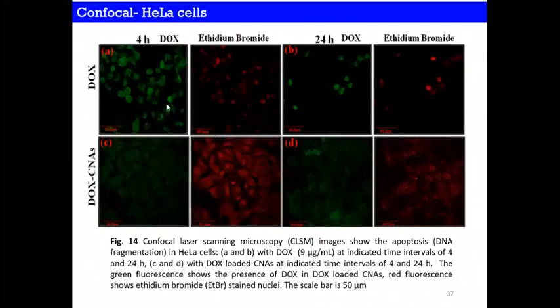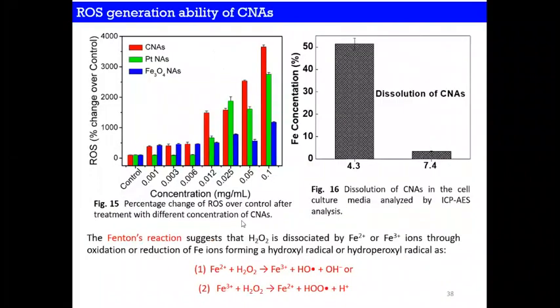Then this is the image of the cancer cell with the DOX. Of course, this is the HeLa cell, and with the DOX, it's getting killed all of a sudden. But with the DOX and the composite assemblies, the nanomaterials loaded with the DOX, you can see that fragmentations are there, sequential apoptosis or controlled apoptosis is there in the cells, and the cell death can be triggered with the application of the magnetic field. Then we also tried hydrogen peroxide. We manually gave around 10 microliter of hydrogen peroxide, and we did the same treatment with DOX and magnetic nanomaterials and hydrogen peroxide, and the cell death is triggered.